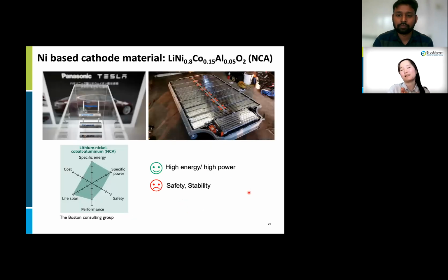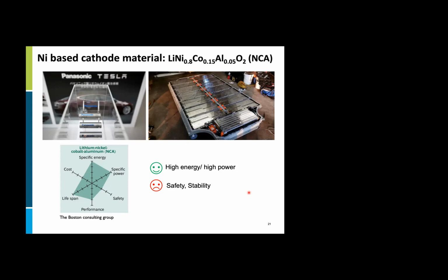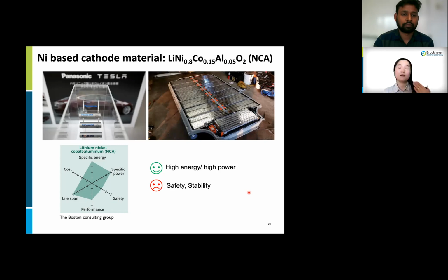I specifically studied a nickel-based cathode material, lithium nickel cobalt aluminum oxide, referred to as NCA, because this material is commercially important and Tesla uses this compound as the cathode material in their electric vehicles. NCA provides high energy density and high power density, but safety and stability have been problematic. So I performed electron microscopy work for diagnosing the incipient material degradation.